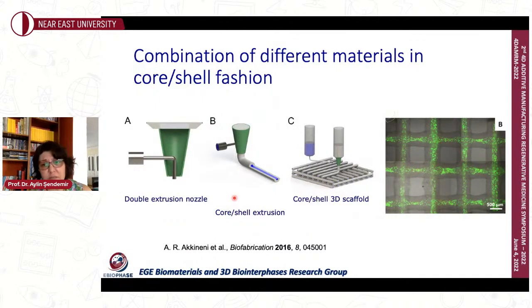Also, another technique, I shouldn't say commonly used, but recently experimentally tried quite often, is core shell printing. So in this case, again, two different nozzles printing two different materials, but not in different layers, but in a core shell fashion. So one layer would be responsible for cellular viability, whereas the other layer would be responsible for structural integrity.